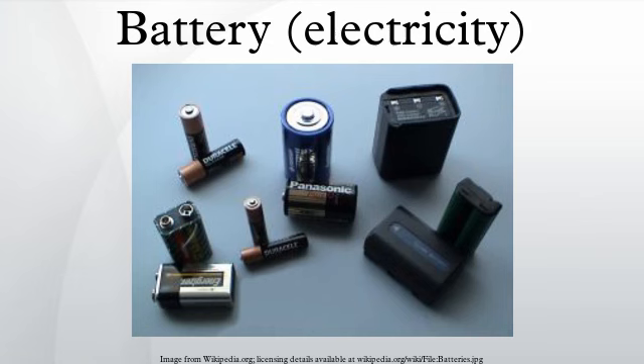When a battery is recharged at an excessive rate, an explosive gas mixture of hydrogen and oxygen may be produced faster than it can escape from within the battery, leading to pressure buildup and eventual bursting of the battery case. In extreme cases, battery acid may spray violently from the casing and cause injury. Overcharging, that is, attempting to charge a battery beyond its electrical capacity, can also lead to a battery explosion, in addition to leakage or irreversible damage. It may also cause damage to the charger or device in which the overcharged battery is later used. In addition, disposing of a battery via incineration may cause an explosion as steam builds up within the sealed case.